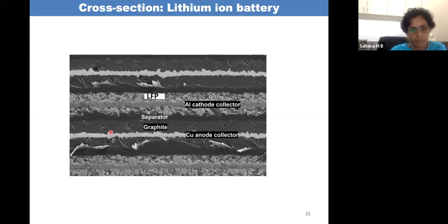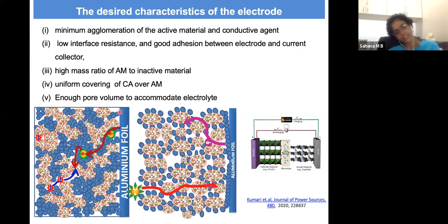So what is the best morphology for an electrode? Let's open up this cell and see what morphology is required for a lithium ion cell. That depends on the material. For graphite, the best morphology may be different. For a cathode with lower electronic conductivity, the best morphology will be different. But one of the main things is that there should be minimum agglomeration of the active material and the conductive agent.